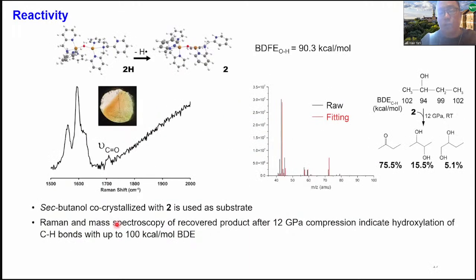That oxyl nature means this bridging oxygen is hungry for hydrogens in terms of hydrogen atom abstraction reactions. We can demonstrate this with the hydroxylation of sec-butanol co-crystallized with our molecule inside the crystal, and we see that oxidation of the sec-butanol generates ketones and diols with pretty high yield.